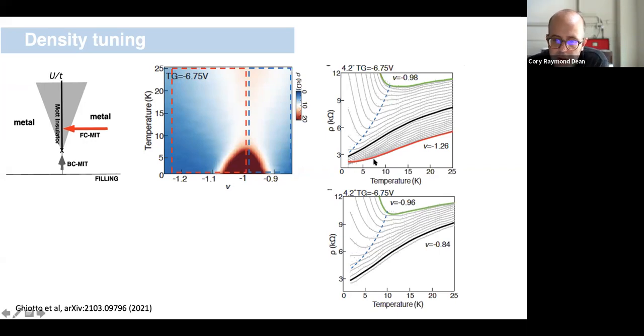Okay, so the red curve here very specifically looks like it's kind of parabolic. The green curve is very clearly insulating. And at some curve between these 2 points here, we have nominally a linear rho versus T dependence from the lowest temperature we can measure in this device up to about 10 Kelvin.